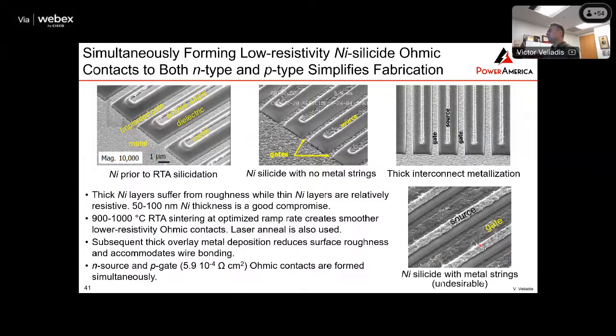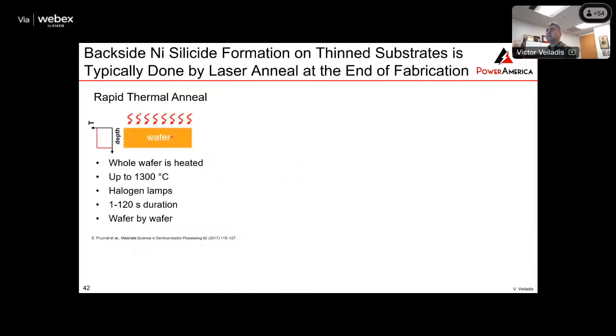And these are older experiments that I've done. Like you can see in this experiment here, where the source is not encased in a dielectric, I get a lot of metal lines, and those can short the device. So you need to develop an ohmic contact process for silicon carbide. And the rapid thermal anneal is done with a halogen lamp. It can go up to 1,300 degrees, and basically you expose the whole wafer to this flash of 1,300 degree light that can last anywhere up to 2 minutes, and you do one wafer at a time.